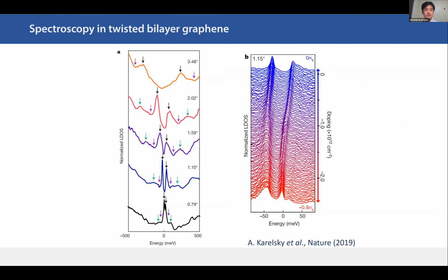Okay, so let's look at Van Hove singularities in this material. This is a scanning tunneling spectroscopy measurement done for twisted bilayer graphene. And we see clearly density of states peaks corresponding to Van Hove singularities. The separation of the two Van Hove singularities varies depending on the twist angle. As we make the twist angle smaller and smaller, we see the bandwidth also becomes smaller, and this enhances the correlation effect in this material.